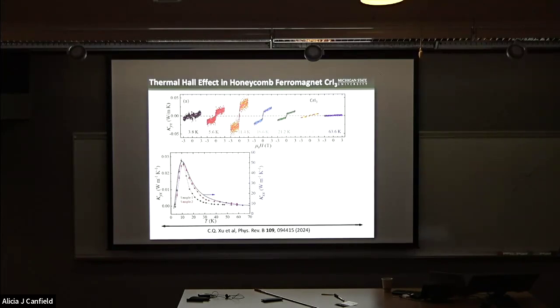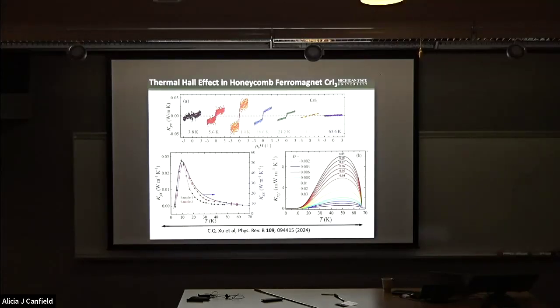magnon-phonon coupling. Interestingly, or surprisingly, at high temperature, we see very small thermal Hall signal. So what's the reason for that? If we assume that at this high temperature the small thermal Hall signal really comes from the topological magnons, as we found in the vanadium triiodide case, then we would expect that the DM interaction will be much smaller than what we expected based on the universal neutron scaling data.